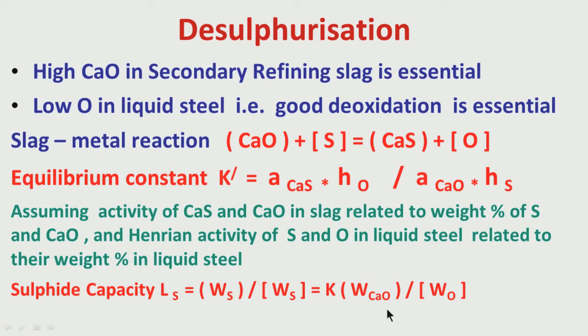Now, this is equal to what? This is equal to 1 divided by k dash, that means another constant, into weight of CaO in slag divided by weight of oxygen in liquid steel. So, just look at this ratio. The sulfide capacity LS, which is an indication of how good the desulfurization is, is basically proportional to the weight of calcium oxide in the slag, divided by the weight of oxygen in liquid steel. That means this is directly proportional to the CaO percentage in slag, but inversely proportional to oxygen present in liquid steel. So, the lower the liquid steel oxygen, the better will be the sulfide capacity, the better will be the desulfurization.